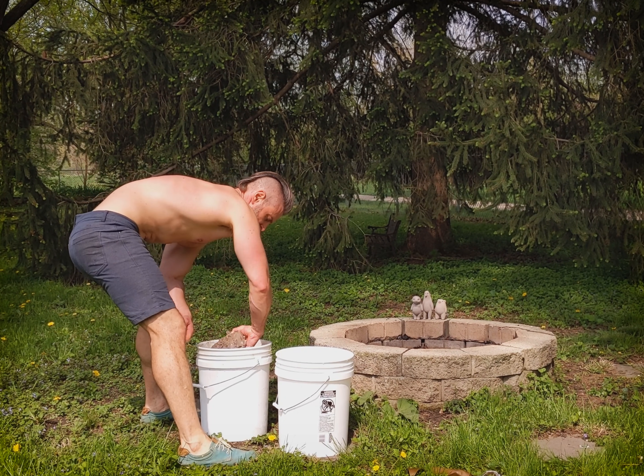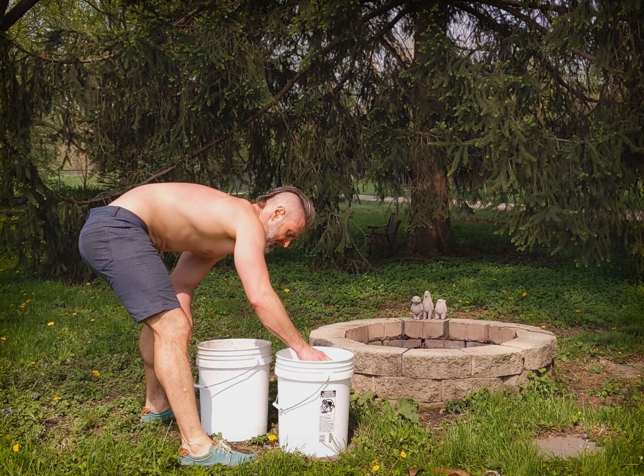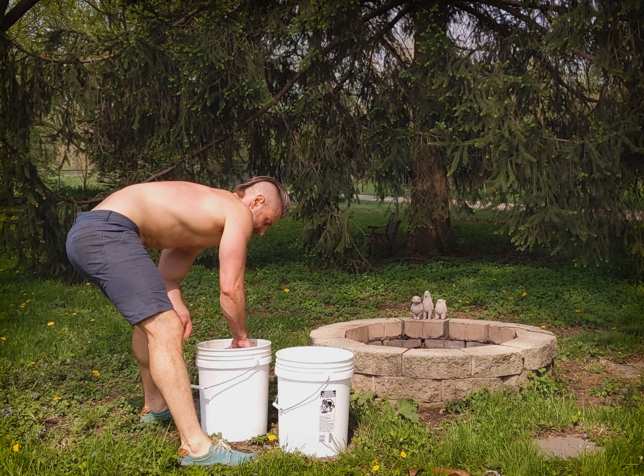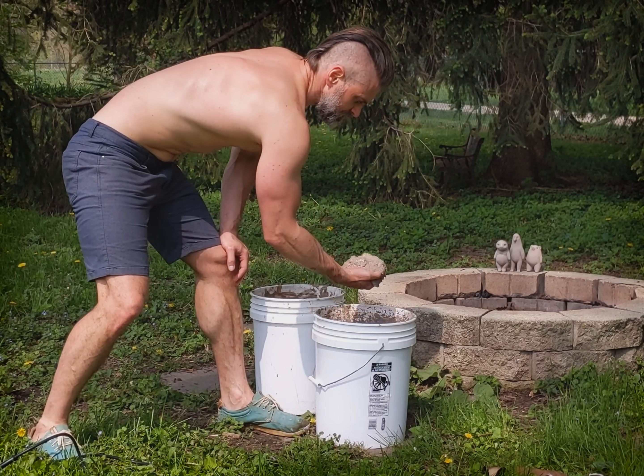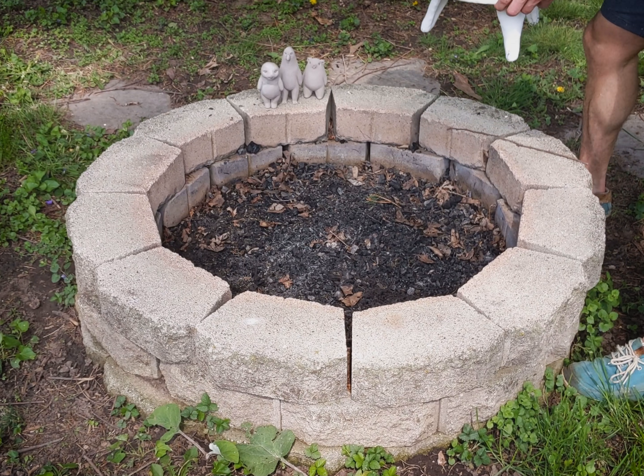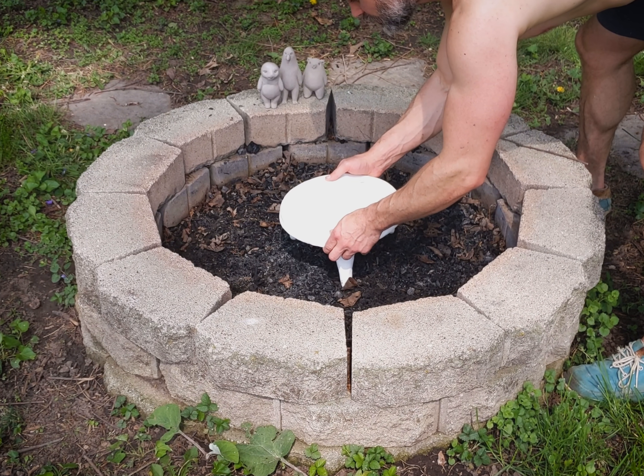All you really have to do to make this kiln is wrap a teepee fire in alternating layers of paper and clay slip. It's just like paper mache. But I'm also adding paper pulp to the slip so it won't flake off as readily as it dries and shrinks. This is a bisqued shelf I made to put the work on and the fire under.